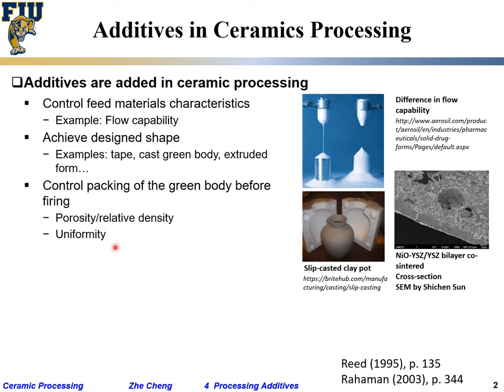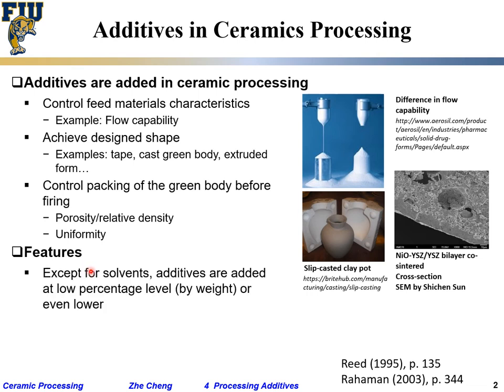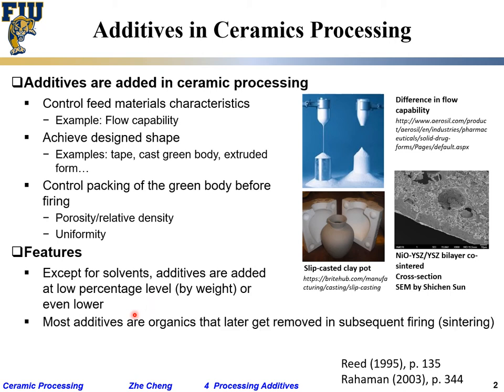Except for solvents like water and alcohol, additives are typically added at a very low percentage by weight — quite often one percent or even much lower — because otherwise they create a lot of trouble. Most additives are organics, which means after typical ceramic processing they are burned away and leave the system, so they don't lead to unwanted properties.